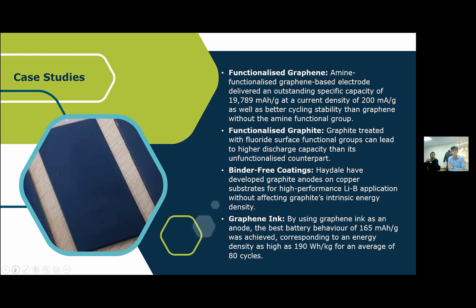So in the image on the left, you could see a copper anode coated with a binder-free coating, which doesn't have resin, just a highly robust graphene-based coating on top, which is mechanically stable and electrically really superior compared to all the inks and additives that they add in resin-based coatings. And finally, the graphene ink that we have is actually capable of producing 165 milliamp hour per gram capacity, which leads to energy density of around 190 watt hour per kilogram, with an average cycle capacity of 80 cycles. This is our standard ink that we use for electrodes.